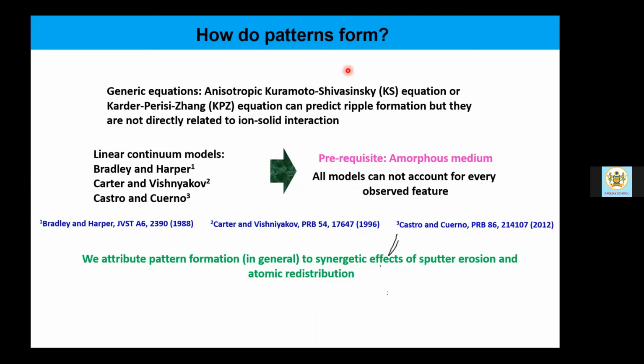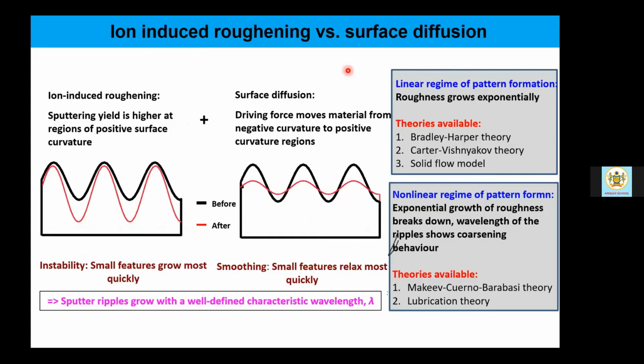So when we talk about ion-matter interaction, ion-solid interaction, then we attribute pattern formation in general to synergetic effects of both sputter erosion and atomic redistribution due to ion-induced surface diffusion. In the case of surface diffusion, it will smoothen the surface from a rough surface, and ion-induced roughening takes place due to sputter erosion. So this is a continuous process. Both are operative. In one case, the surface is getting roughened, but at the same time, ion-induced surface diffusion is trying to kill those roughened parts and give a smoothing touch. So small features relax most quickly and small features grow most quickly under ion-induced surface diffusion and ion-induced roughening modes, respectively.